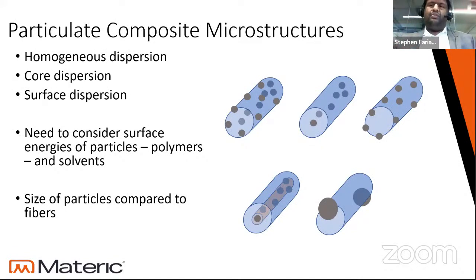Where if the opposite is true, where then the polymer material really wants to be more interfaced with the solvent, then you might get particles that are almost purely in the core of the fiber. Or if it's mixed, you might get some homogeneous dispersion of particles in the fiber.